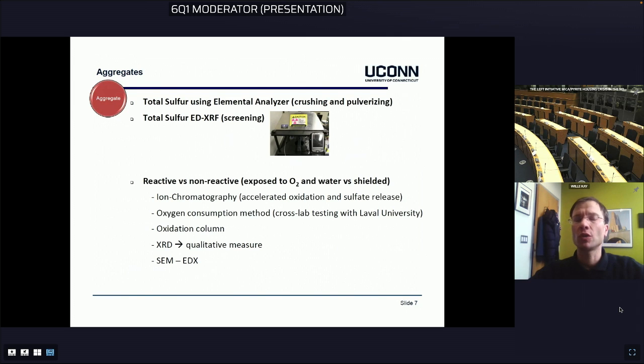And then with the aggregates, you not only want to know whether sulfur and other iron sulfides are present, you also want to know how much is the chance of being reactive or not, and so whether those metal sulfides are exposed to oxygen and water, or whether they might be shielded, for example. So you could use ion chromatography to accelerate the oxidation and measure the sulfate release. You can use the oxygen consumption method as developed with Benoit's group, and we are involved in this cross-lab testing with Laval University. Here at UCONN we have developed and built oxidation columns. I'll show this in a second. You can also use XRD for qualitative measure, and of course SEM using EDX.